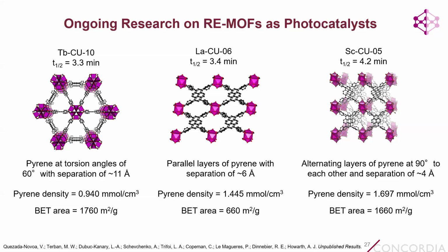Whereas in lanthanum CU-06 and CU-05, even though we have this really high density of pyrene chromophores, they're stacked in relation to each other and very close. So in CU-06, they're parallel to each other with a separation of only 6 angstroms. And in CU-05, they're alternating layers at 90 degrees to each other, but with a separation of only 4 angstroms. So we think that in these structures, we can generate more excimer formation, meaning that excimer formation is competing with the generation of singlet oxygen and making these catalysts not quite as fast as CU-10.